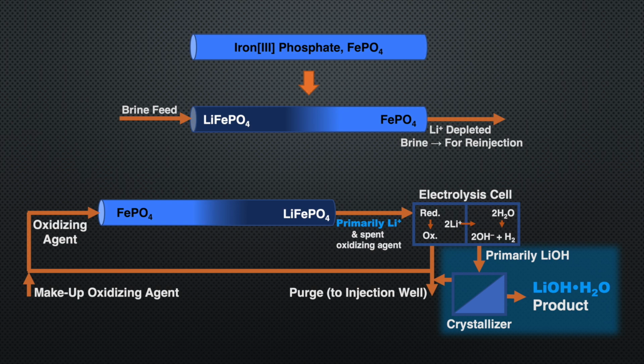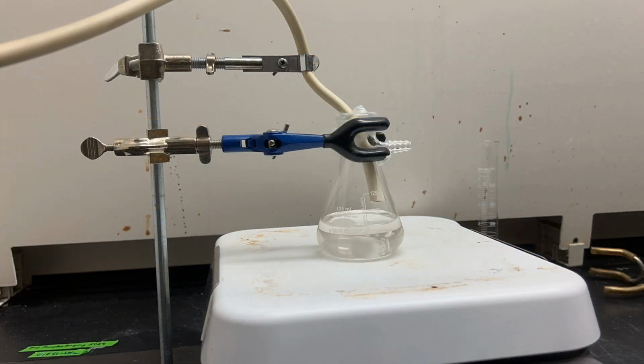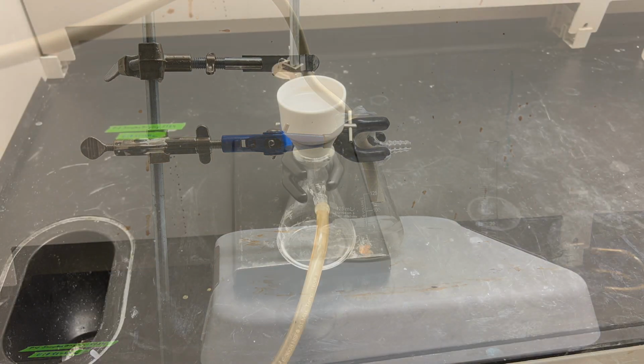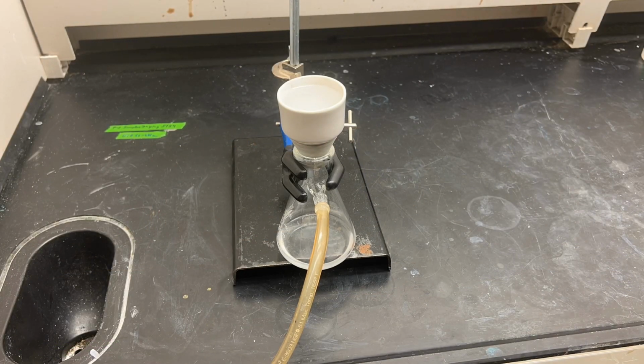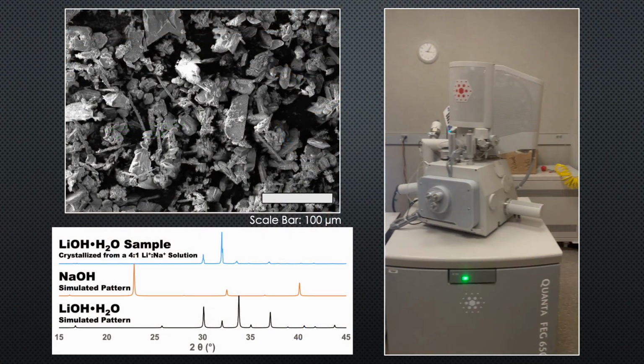Finally, the lithium hydroxide solution can be dewatered in a crystallization process where water is recovered elsewhere. The resulting lithium hydroxide crystals are recovered via filtration and imaged using SEM. The purity of the product crystals can be verified using XRD.